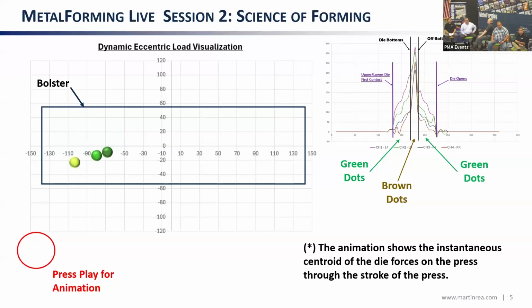The load starts very close to the end of the bolster. It moves around while the die is closed, and then as the die is opening, the nitrogen cylinders and all of the die components are still applying the same force on the way up as they did on the way down.